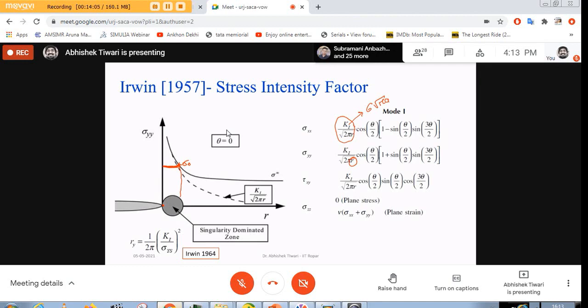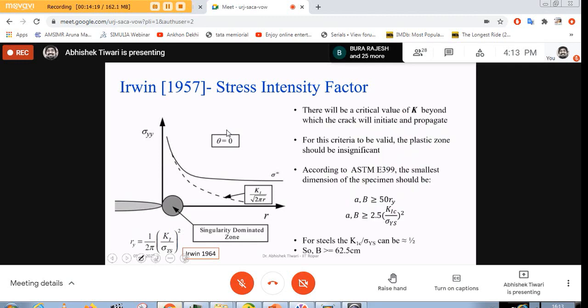Irwin didn't know much about how to solve the equations in the plastic zone, so he said to make sure that your plastic zone is very small, and then you can still deal with the theory of elasticity. And so that idea was standardized in the form of ASTM E399. It is also used even today for brittle materials like glasses and ceramics. The constraint which it imposes on the specimen is that the smallest dimension of the specimen should be greater than 50 times the plastic zone radius.